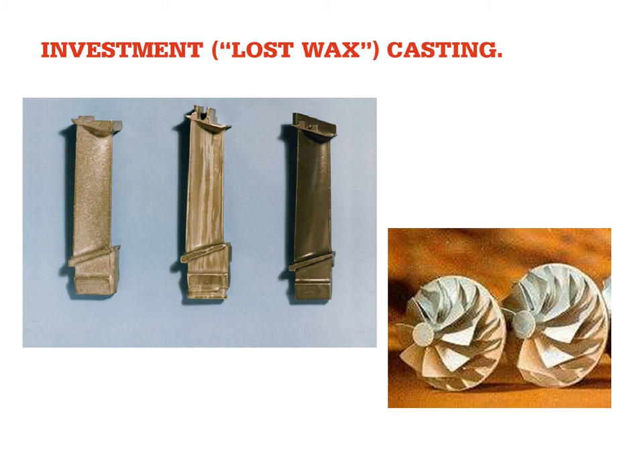generic forms of casting. The lost wax process, or investment casting, is used for the turbine blades. It's also used for things like impellers. And here we make a model of the piece that we are going to produce in wax. We then coat that wax with a ceramic high temperature refractory material. We bake that to cure the ceramic material and melt the wax. So we then have a ceramic shell with a cavity of the correct shape.